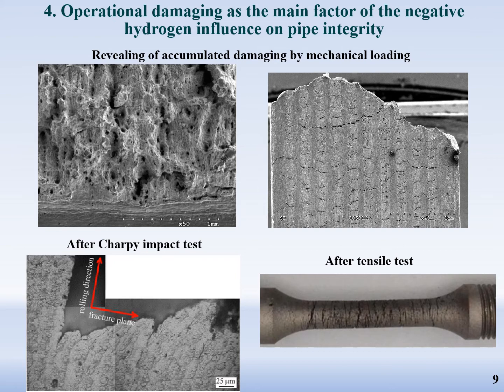Here you can see some examples of revealing of damage accumulation by mechanical loading. Namely, you can see in-bulk pipe wall dissipated damaging on the fracture surface after impact strength and usual tensile tests of specimens. And you can see how preliminary cathodic hydrogenation accelerated micro damaging. One important thing should be noted: more intensive damaging is in the rolling direction. Therefore, specimens cut in the transversal direction to the pipe axis should be more sensitive to operational degradation.